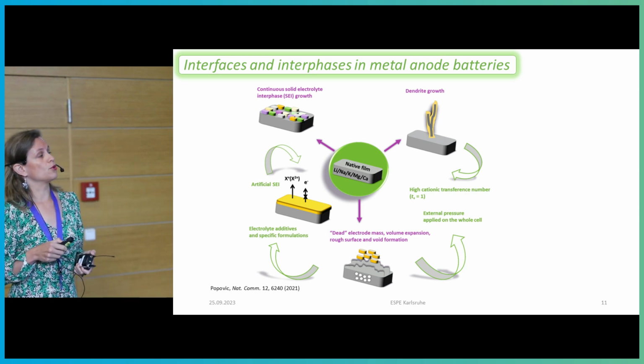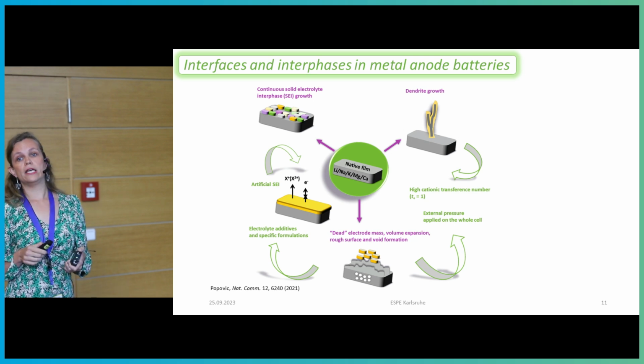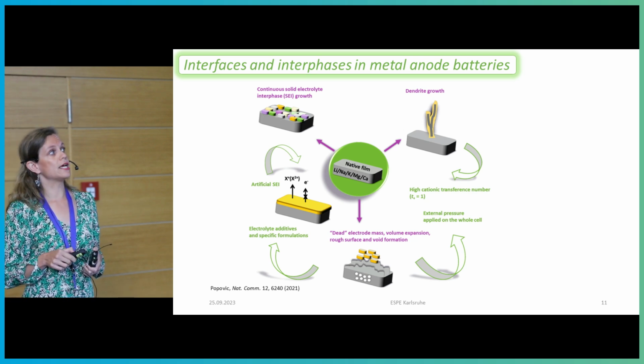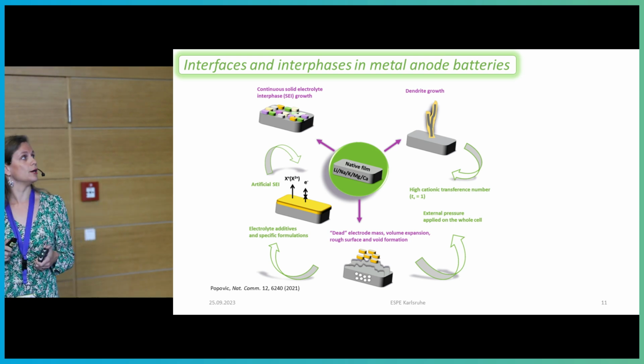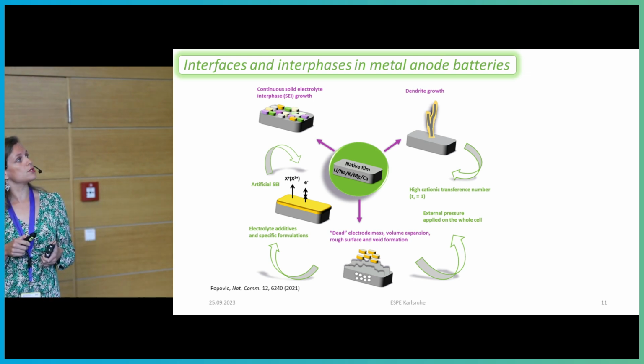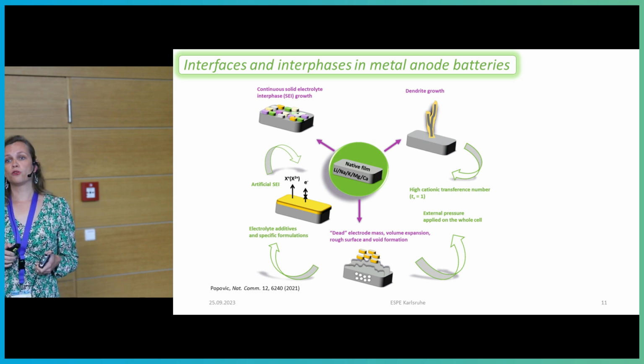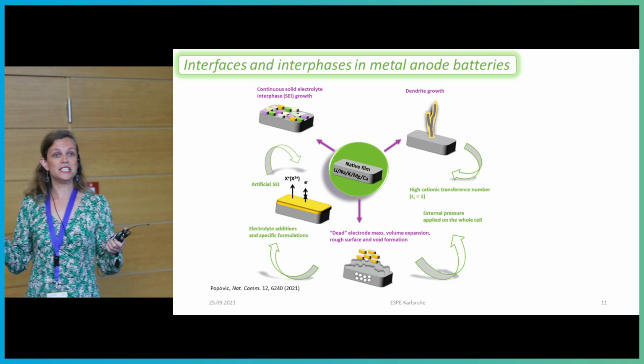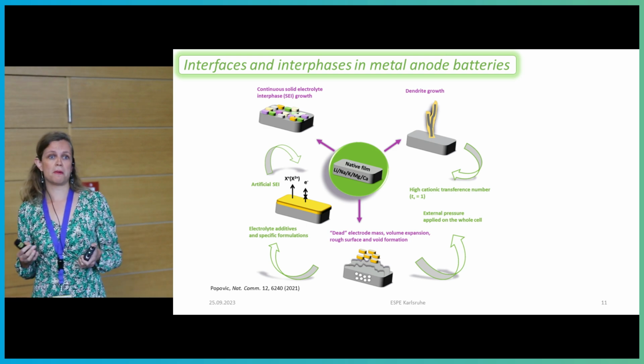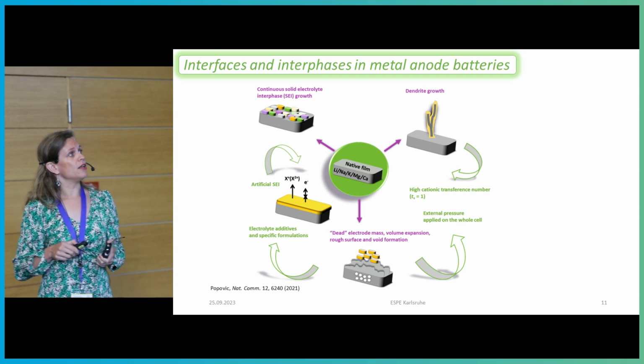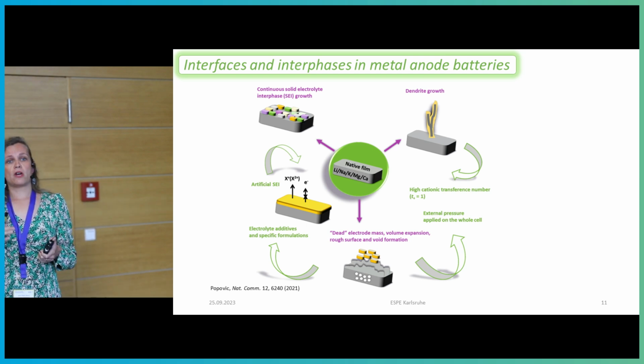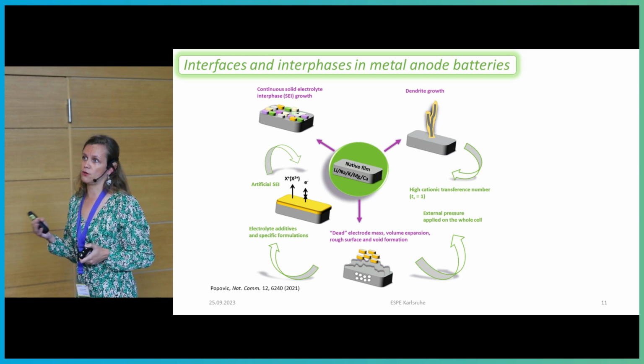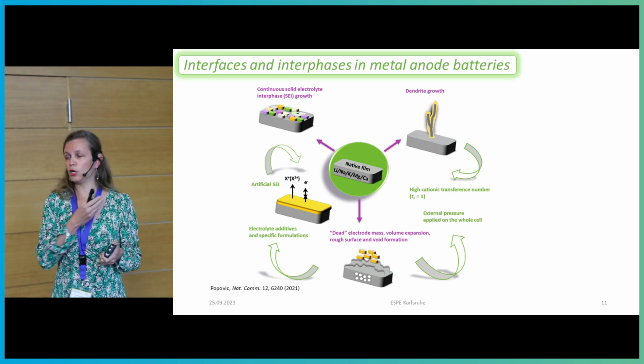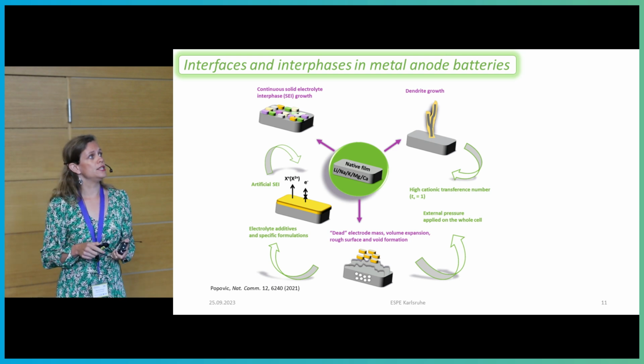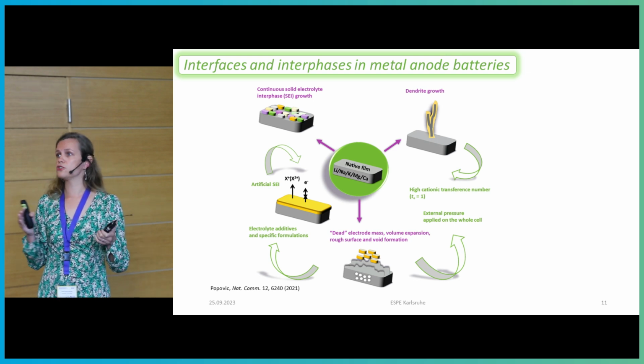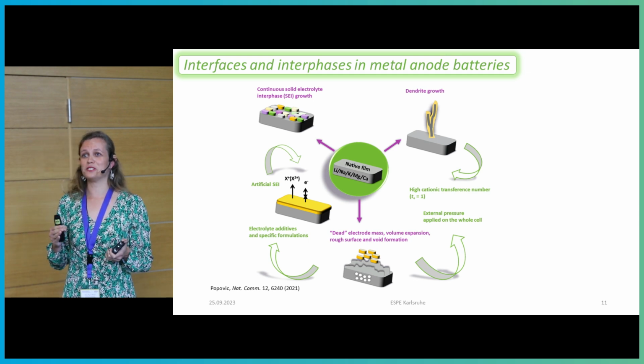And how do we deal with dendrite growth? Well, people have tried so far to employ artificial SEIs as a kind of cure for the continuous SEI growth situation, but we also know that there is a really big body of work on additives, which are kind of secret sauce to make batteries work. On the other hand, for dendrite growth, we might try to use materials that have high cationic transference number. This is one of the options if we look at the crossover current values. The other way is applying external pressure and trying to press those dendrites away.